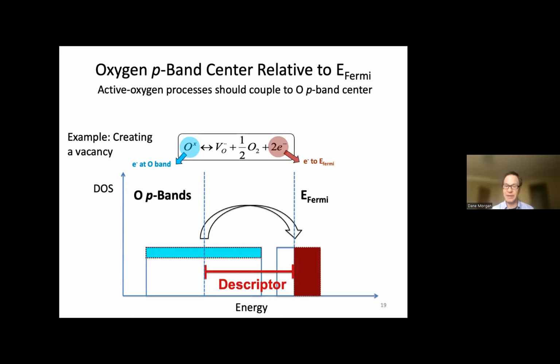And I would argue that yes, because when oxygen moves in and out of a material, it generally causes redox in the material. It either pulls electrons to the oxygen or drops electrons back in the material. So here's an example where you create a vacancy in an oxide. If you create a vacancy in an oxide, the oxygen usually has 2 electrons sitting on it. And when you pull the oxygen out of the material, those 2 extra electrons that the oxygen pulled from cations in the oxide get dumped back into the oxide. If you think qualitatively what that involves, it means the oxygen P-bands that used to hold those 2 extra electrons drop them at the Fermi level. That's essentially what happens in terms of redox when you create a vacancy.